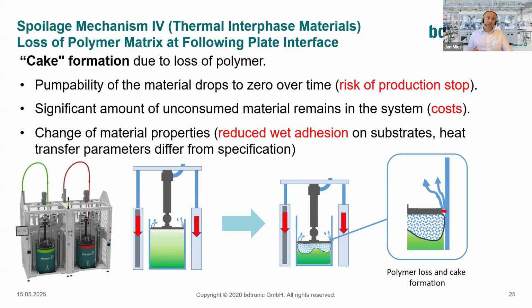Another thing is that when you lose polymer matrix, you change, of course, the final properties of your thermal interface material. That means you get a reduced wet adhesion that could jeopardize the application process. I think Till will show us later on some pictures of it.